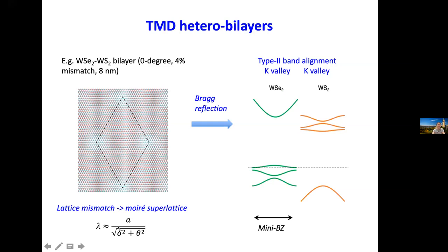This significantly reduces the effect of twist angle disorder, as we have seen in the bilayer graphene system. And then the long wavelength moiré potential causes Bragg diffraction of electrons and leads to moiré minibands. Here I'm only showing you the lowest energy conduction and valence moiré minibands.